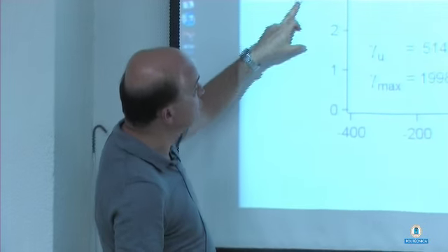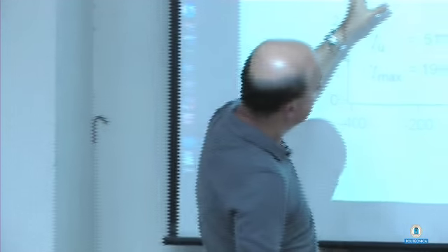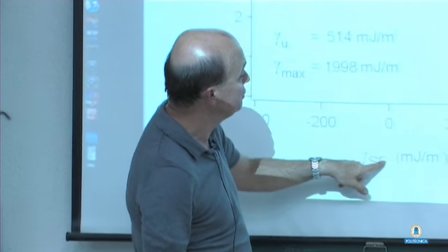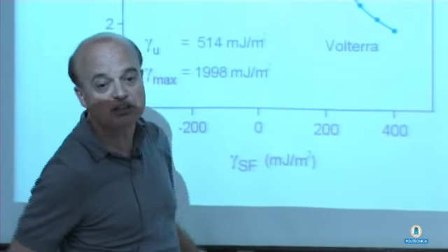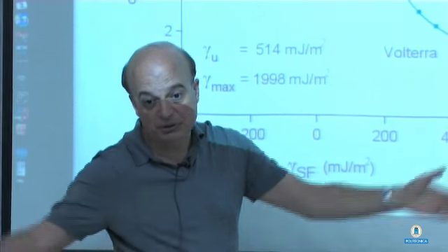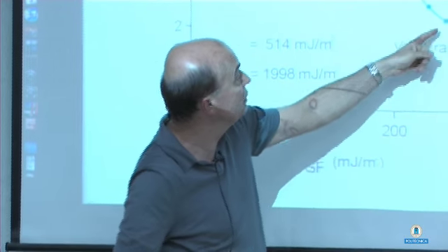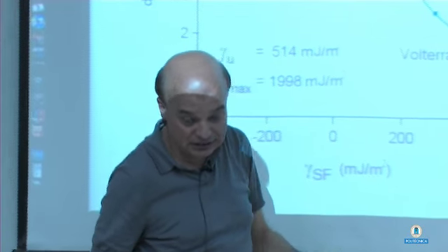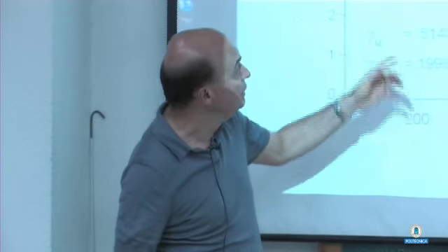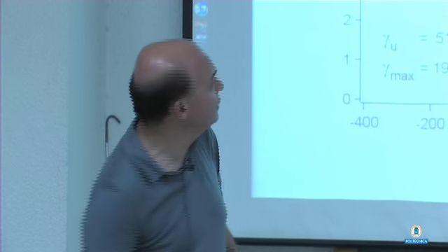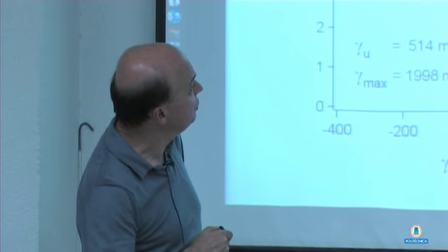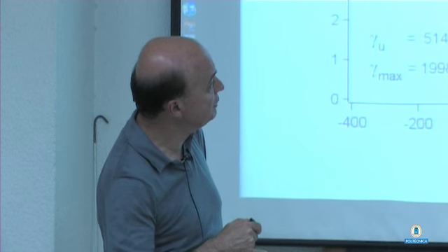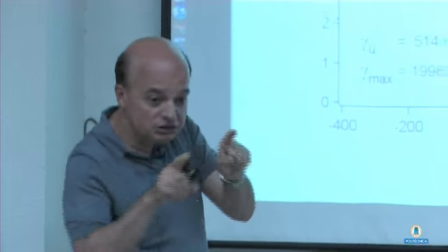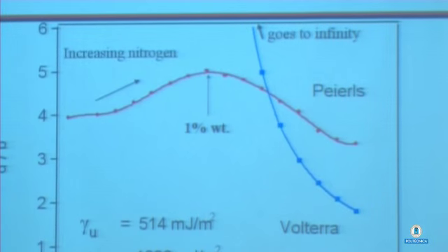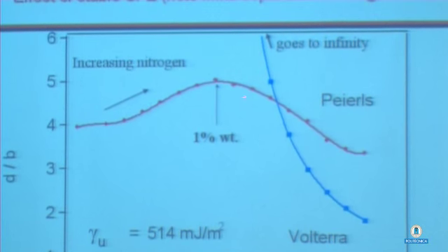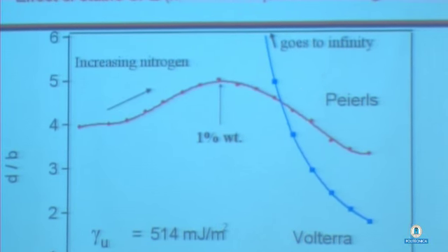And what happens is that the width, d, as a function of intrinsic stacking fault energy: we teach our students that if the intrinsic stacking fault energy is 0, the width should be infinity. That's for a Volterra dislocation, goes to infinity. But that's not the case, because we have to look at the entire gamma curve. In fact, if you keep increasing the nitrogen, around 1% nitrogen weight percent, the separation width is maximum, and after that it starts decreasing again. So this corresponds to the highest strength point, so you can predict that as well.